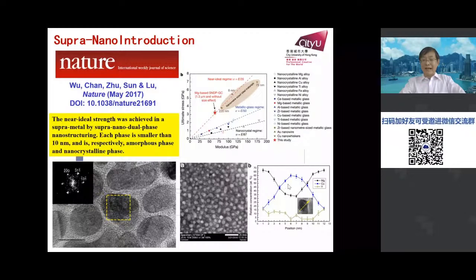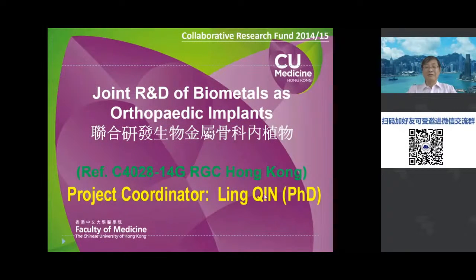As you may see here, the chemical composition is quite amazing. We have a continuous change of chemical composition, but at the heart of this structure, we have a copper-rich structure inside of the crystal, and here is magnesium-rich. So what's the potential application for this new structure? The first example is orthopedic implants using the magnesium alloy. I will just present this study conducted by Professor Ling Qin of the Chinese University using our material.